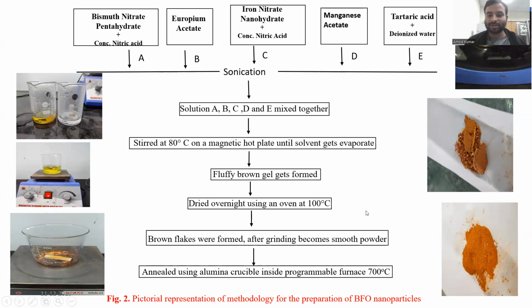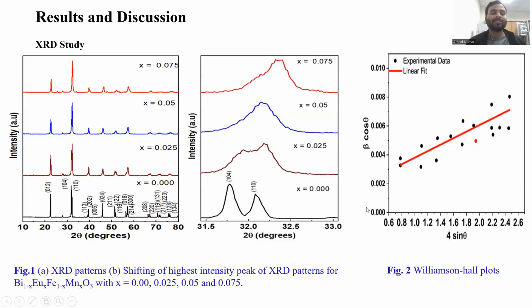So I go further. After several attempts, I prepare the BFO and substitute some percentages, some substitution of Eu and Mn at 2.5%, 5%, and 7.5%. So these are the XRD of the doping. This figure is the intense peak, and this is the zoomed part of the intense peak.